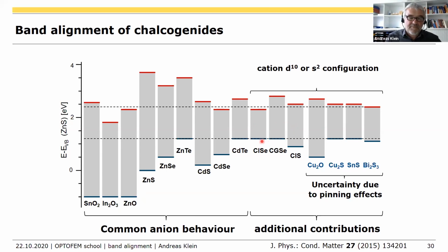Surprisingly, the copper indium selenide valence band is not here, although it also contains selenium. The reason is that in copper indium selenide we do not have only selenium contributing to the valence band, but also copper. Copper has a very shallow 3d level, just about 2 or 3 eV below the maximum of the valence band. The copper d states hybridize a lot with the selenium states, and this is what Alex Zunger in his papers calls pd repulsion. So the valence band maximum is higher in energy, about 1 eV, if you add the copper here.